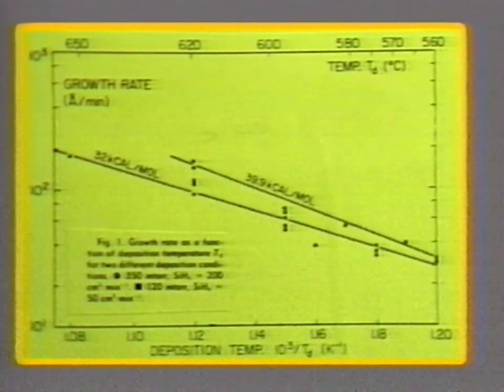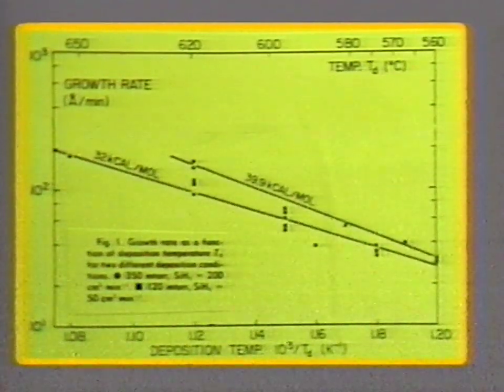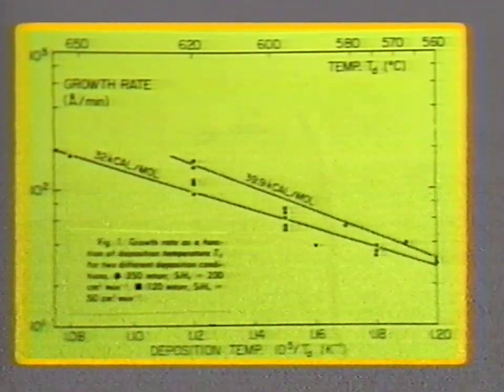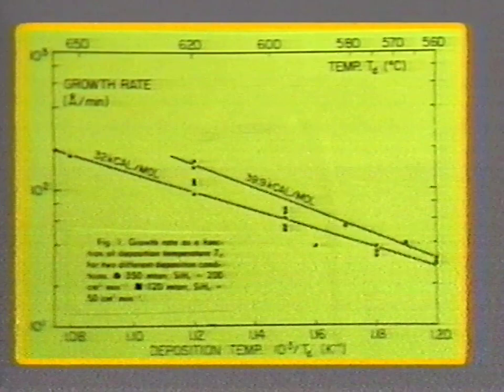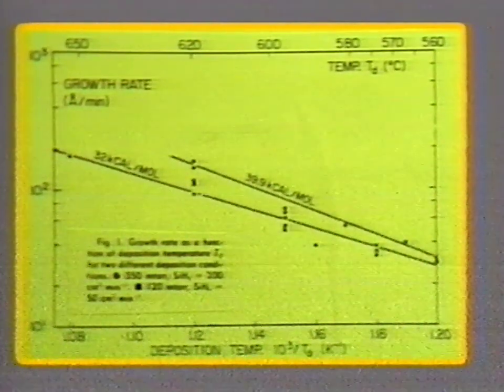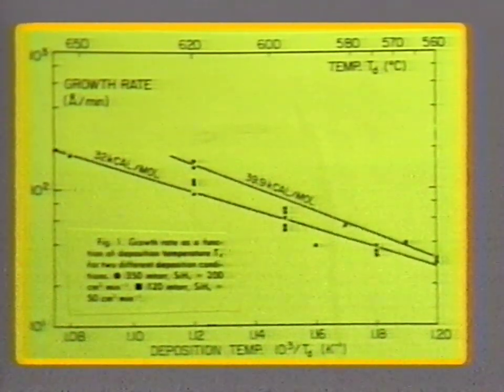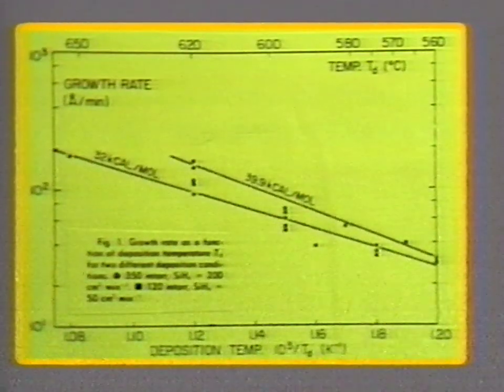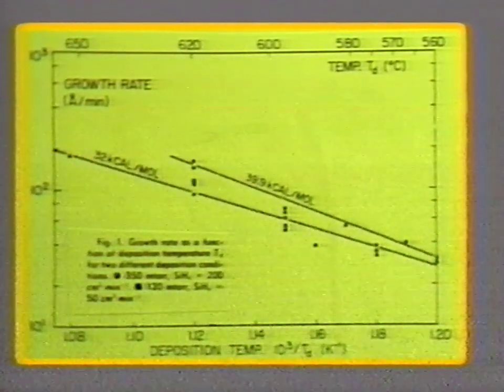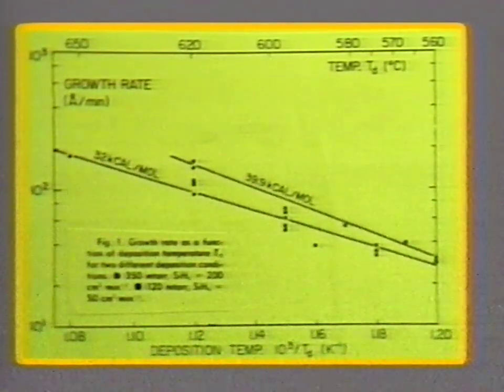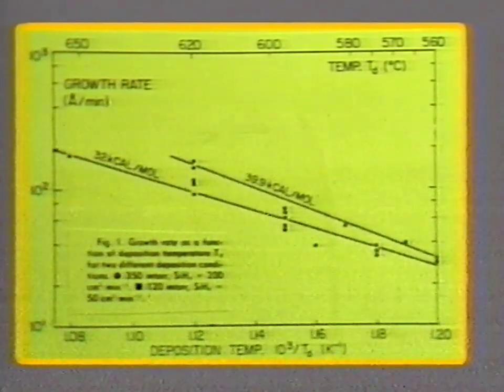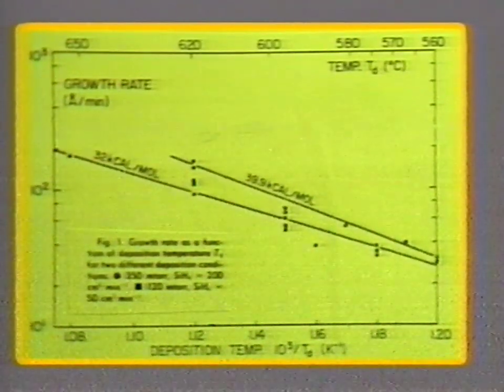Typical deposition rates, as you can see, are in the range of about 100 angstroms per minute, and of course the temperature range used for the amorphous type film is up to about 580, and the higher temperatures are used for the polycrystalline film formation.